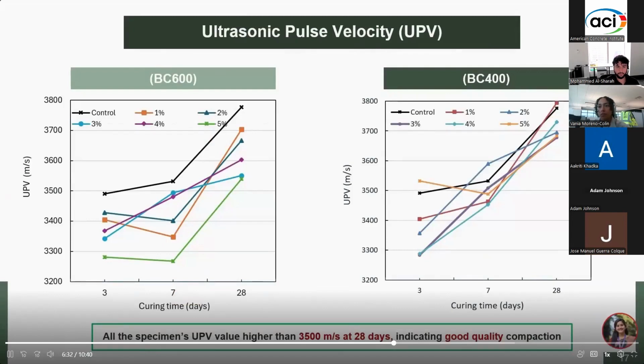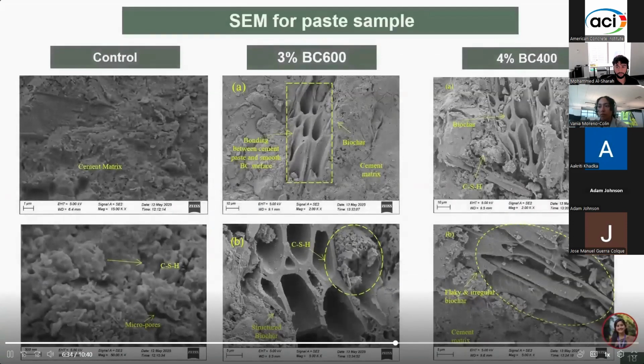Now let's see the SEM of the paste sample. In the strength parameter, BC 400 was better than the BC 600 because BC 400 has a more irregular and rough surface and it is capable of making a bond with cement easily compared to BC 600, as you can see in the second and third columns.